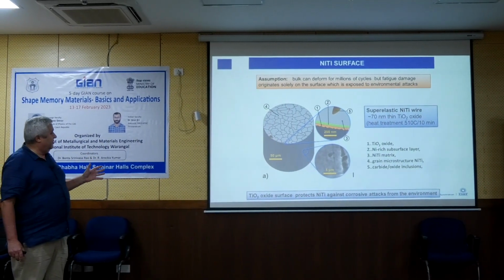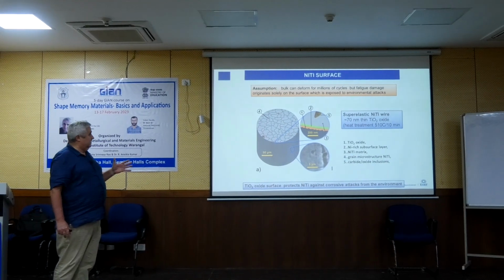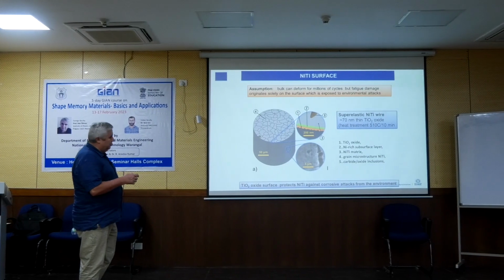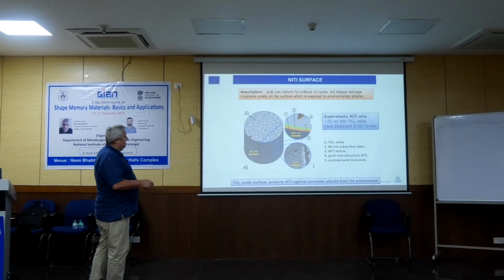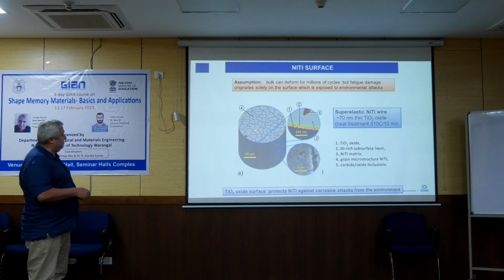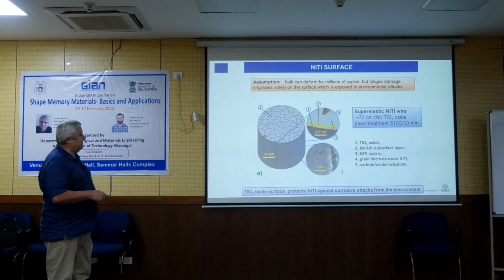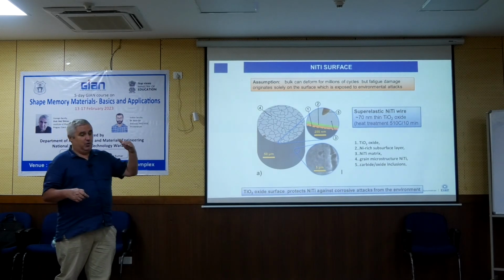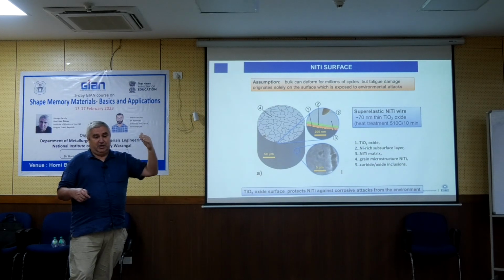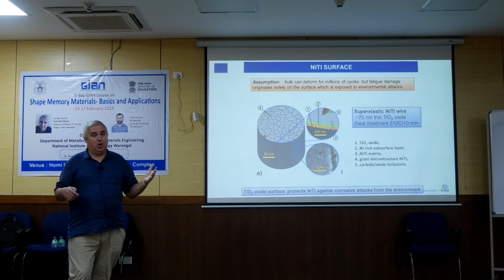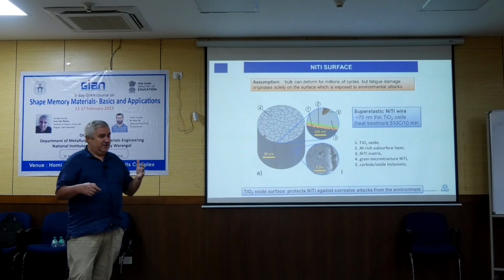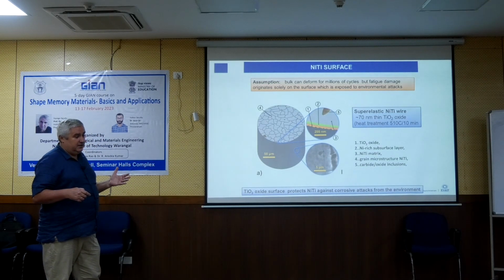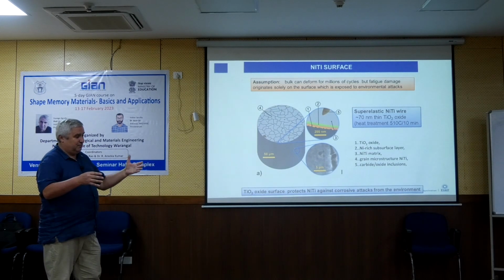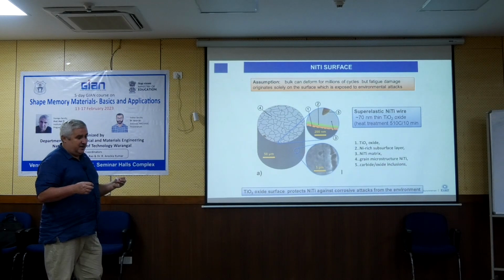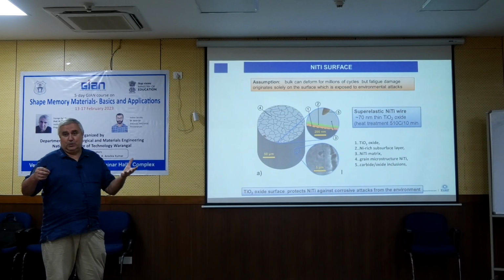So I spoke about the cracks in the surface oxide. Let's look again at how the surface of a nitinol wire, which is used in application, looks like. Because of titanium in nickel titanium, if the nitinol is exposed to atmosphere, it will start immediately to oxidize and form an oxide. If you expose it at a higher temperature, there will be a thicker oxide. If you do it at room temperature only, it will grow for days or years, and it will be uncontrolled. So what is done normally in any company which makes the semi-products for medical devices is that they electropolish the surface and then perform some controlled oxidation in a controlled atmosphere for a short time.